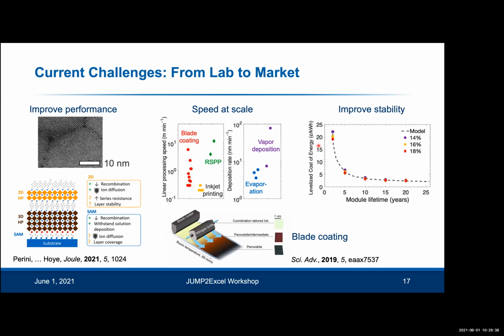And the third important factor is, of course, stability. And that is really encapsulated by this figure here, which calculates the levelized cost of energy versus the lifetime. And you can see that beyond a 5-year module lifetime, changing the efficiencies doesn't really make a huge difference anymore to the levelized cost of energy. It's really the module lifetime that has a bigger effect. So developing a better understanding of what are the main degradation pathways in perovskite solar cells, and developing protocols to do accelerated testing of the stability will be important in the future.